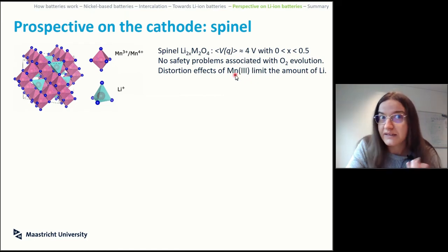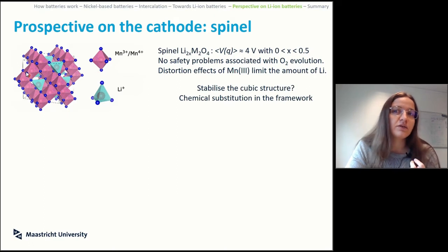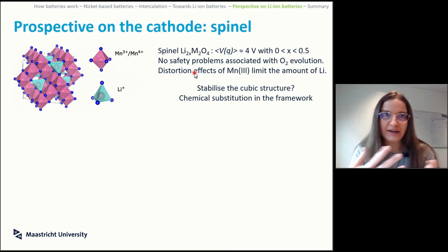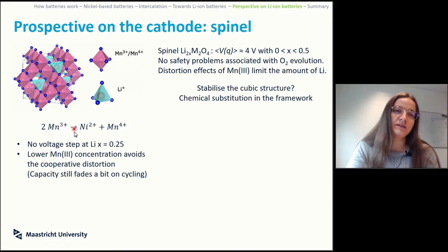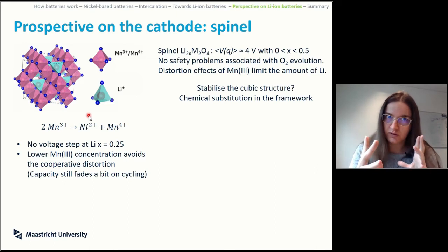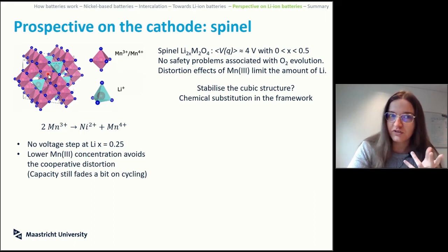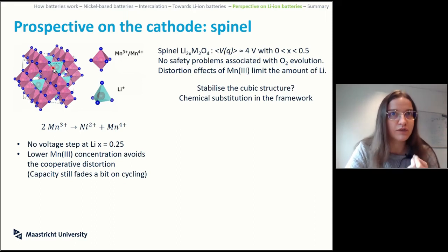So this manganese will limit the amount of lithium. Can you stabilize this? Can you make sure that this avalanche of Jahn-Teller distortions, distorting the whole structure and changing the voltage, doesn't happen? One of the many things that we like to do: throw another atom in, see if it stabilizes the whole business. So instead of having 2 manganese 3 plus, you could have the same charge distribution, something that is equivalent in terms of stoichiometry of charges, but different in terms of stoichiometry of materials.